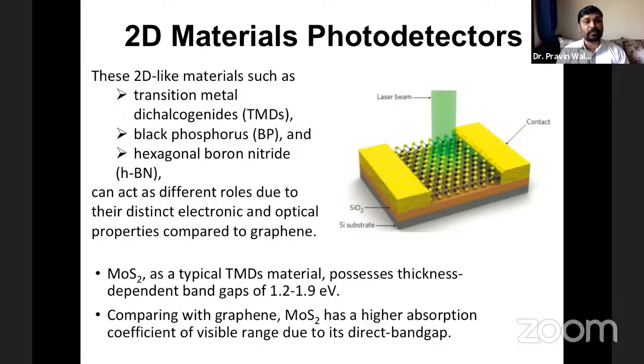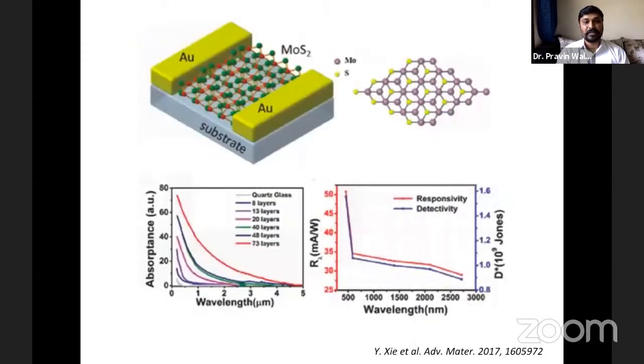Compared to graphene, what is the advantage of MoS2? MoS2 has a very high absorption coefficient in the visible range because of its direct band gap. Here is an example that Xie et al. have already reported in Advanced Materials. If you change the number of layers of MoS2, you see how the absorptance with respect to wavelength changes. With an increasing number of layers, the absorption is improved because of light-matter interaction, and therefore the absorbance with respect to wavelength improves.